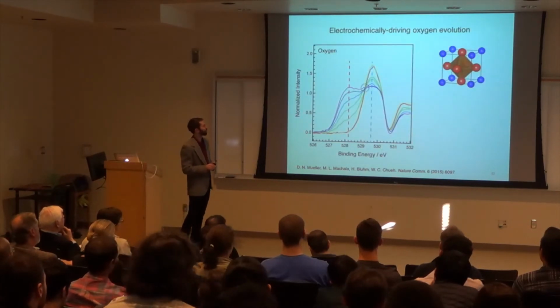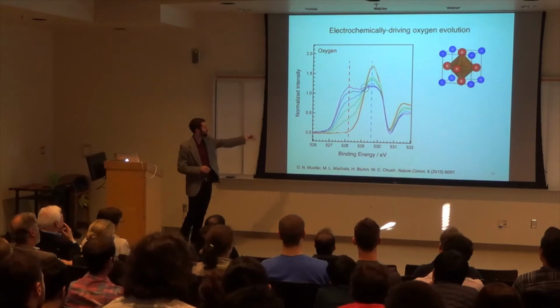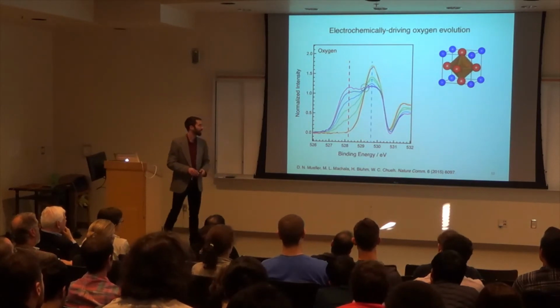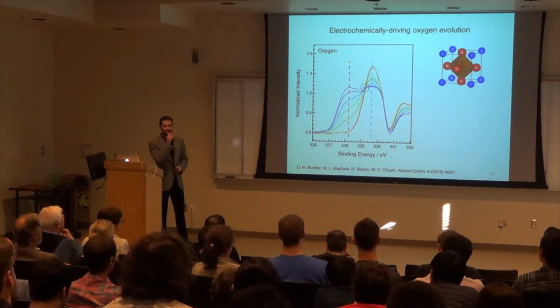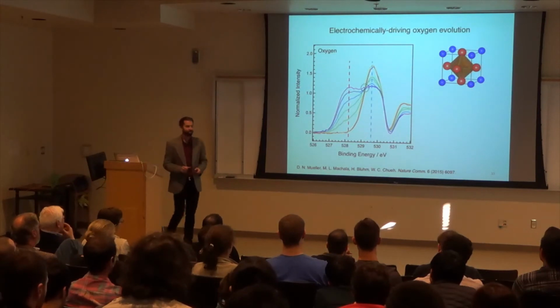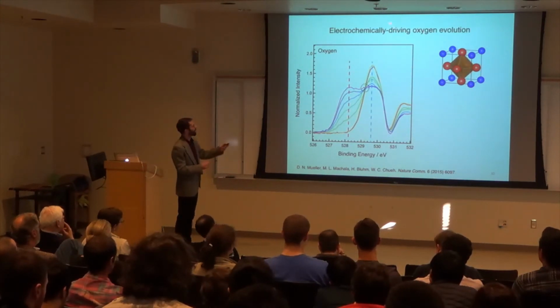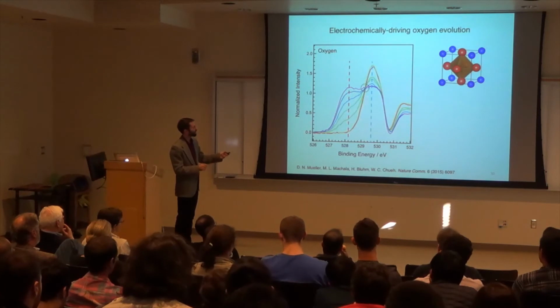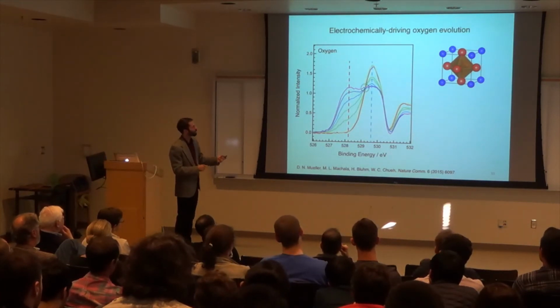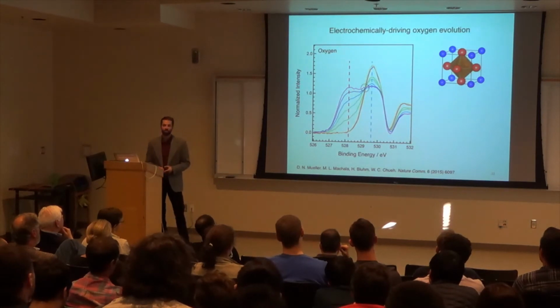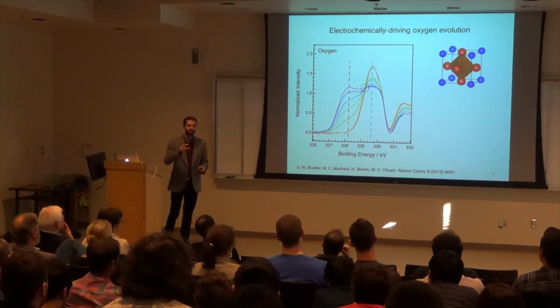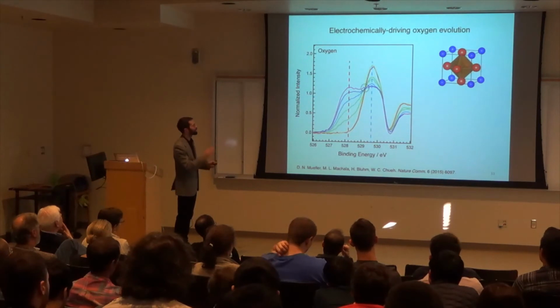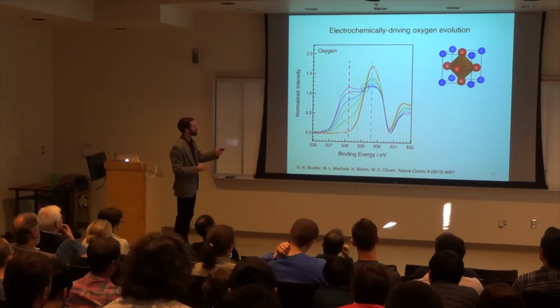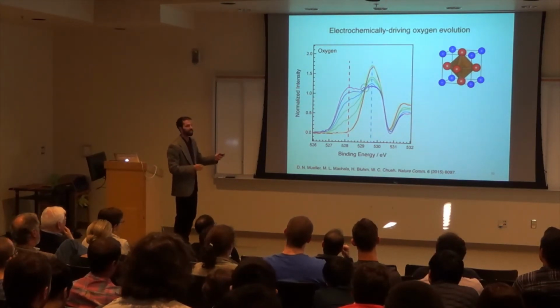So you might have guessed already that there's something else that we haven't talked about yet, and that's the oxygen. This is the oxygen K-edge absorption spectra. We have the normalized intensity on the y-axis as a function of photon energy, sorry, not binding energy. And what we see here is that the spectra is changing pretty significantly as we try to run this reaction. And the area where they overlay is called an isosbestic point. And when you have two different things changing, they create what is called an isosbestic point. And so that means that there is one distinct state here and another distinct state here.